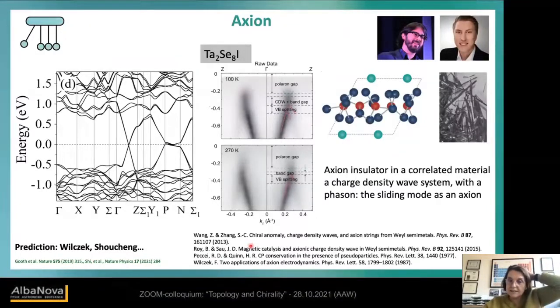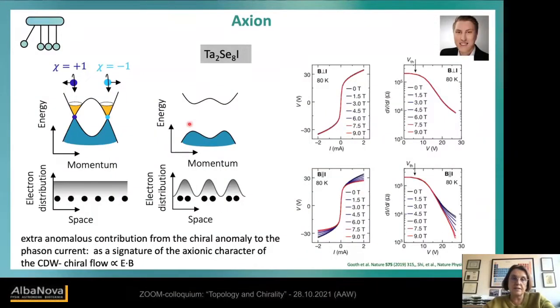But then we recognized that in this paper from 2013, Shoucheng already predicted a chiral anomaly, charge density wave, and axion strings from Weyl semimetals. So learning from this, we recognized that if you have this situation, you might be able to slide the charge density wave, so get rid of it to get back to the Weyl physics. And this is drawn here in the sketch. Because of the charge density wave, we open up a band gap, so we lift the degeneracy. But if we could bring it back, we could see the axion, the axion related to the charge density wave phason. And this was exactly done in this experiment.